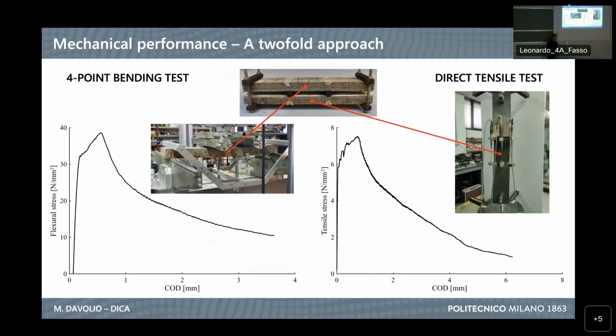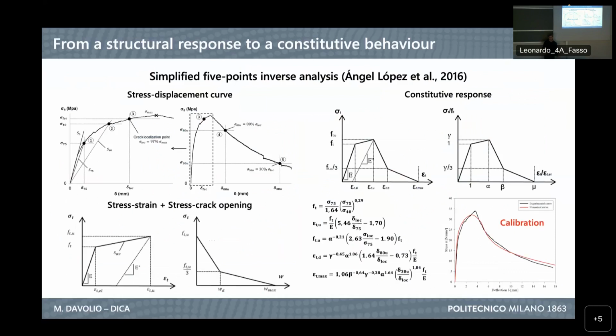For the failure test, we have a twofold approach. As I already mentioned, one of the 2 specimens from the couple was tested under 4-point bending, and the other one under direct tensile test. The last step of the methodology was to develop a method to obtain a constitutive behavior, because this is what I mentioned as our goal for the work. The problem is that for flexural tests, we only have a structural response for the specimen. And for this reason, we took a simplified inverse analysis method from literature, and we adapted it to our case with the purpose of obtaining from our 4-point bending test a constitutive response. We derived these numerical correlations between the test and the constitutive law. And as you can see, we also controlled the calibration of the method, which was quite satisfying, and for this reason, we applied it.